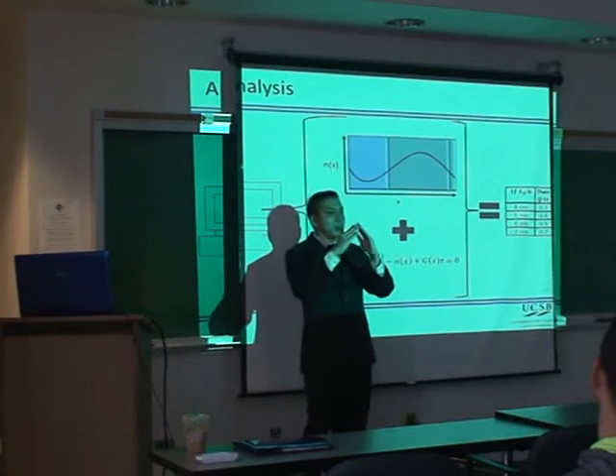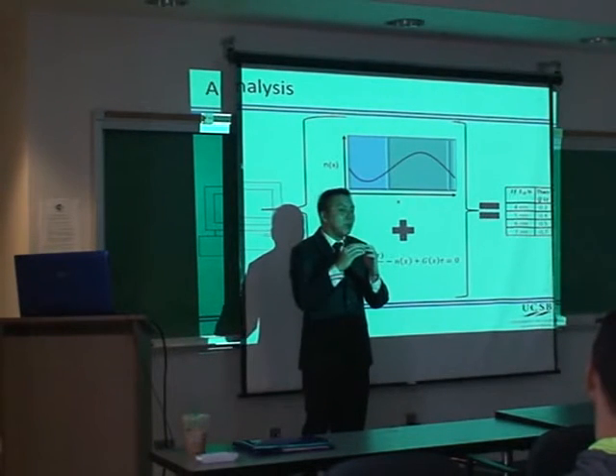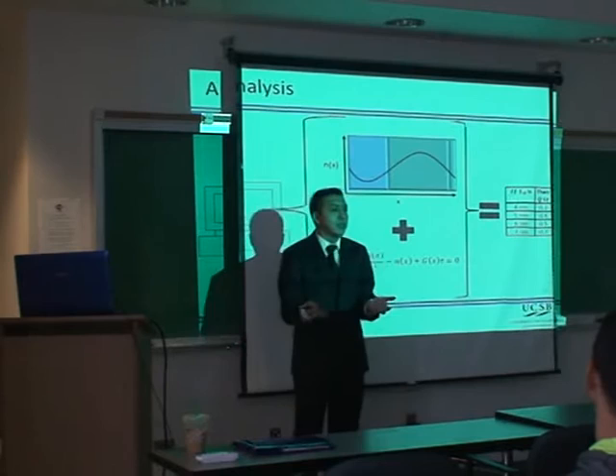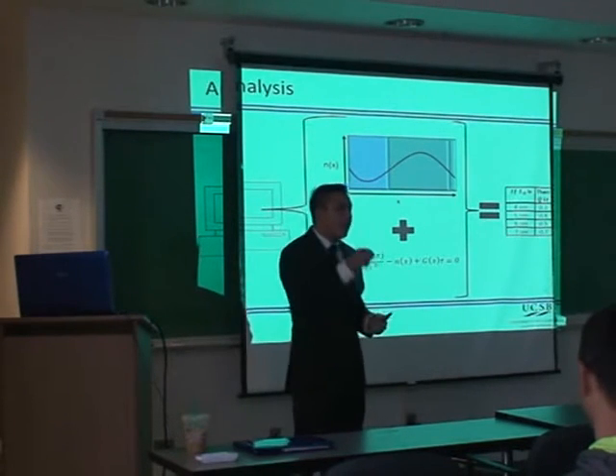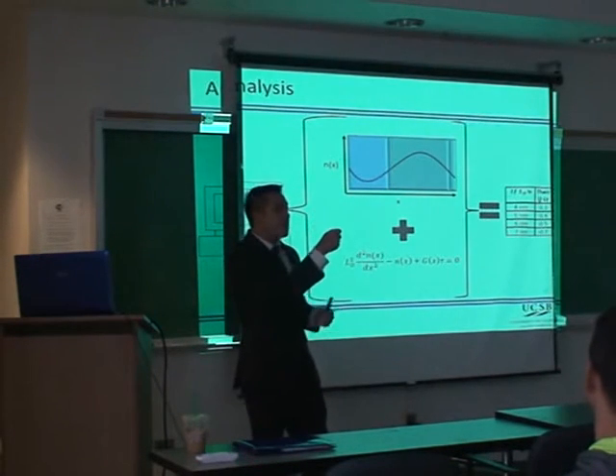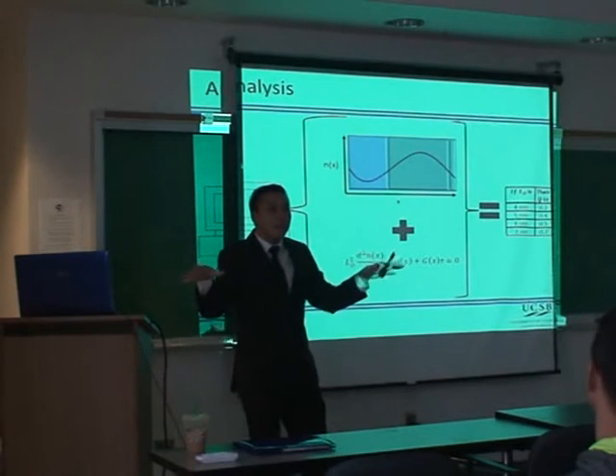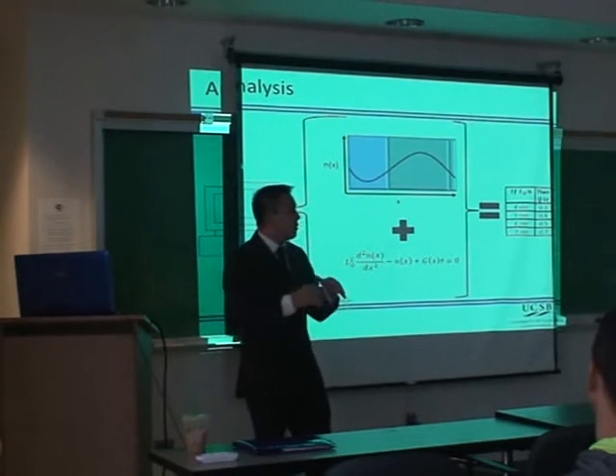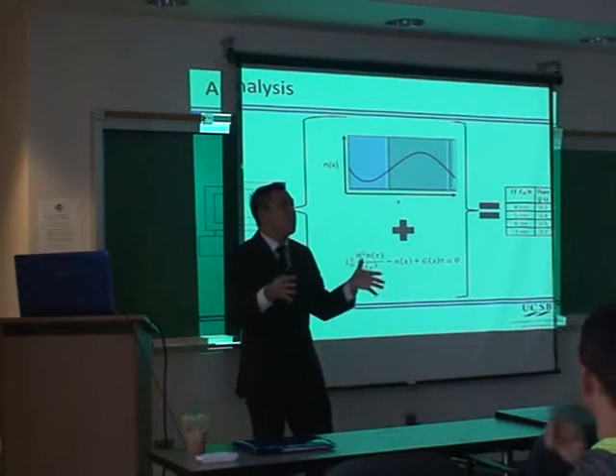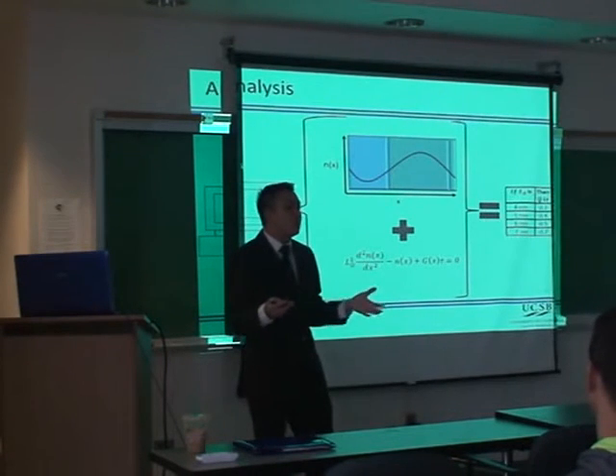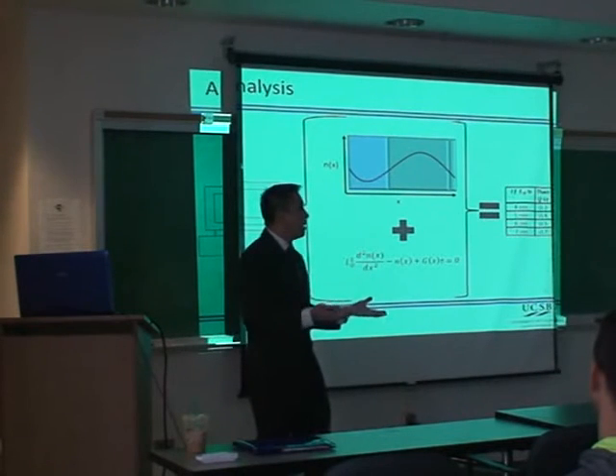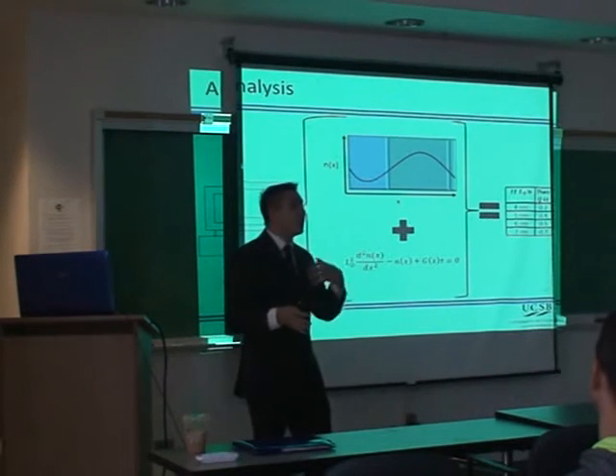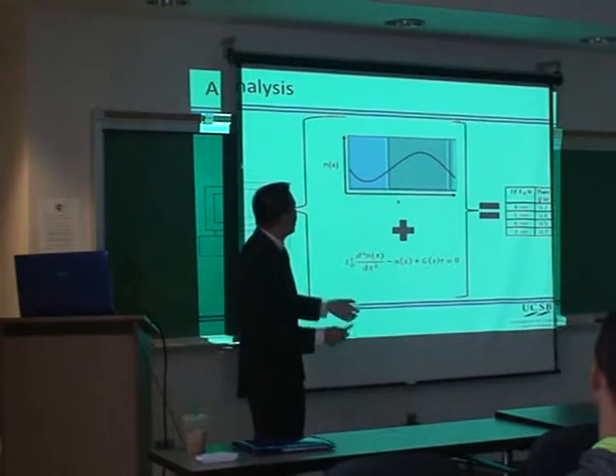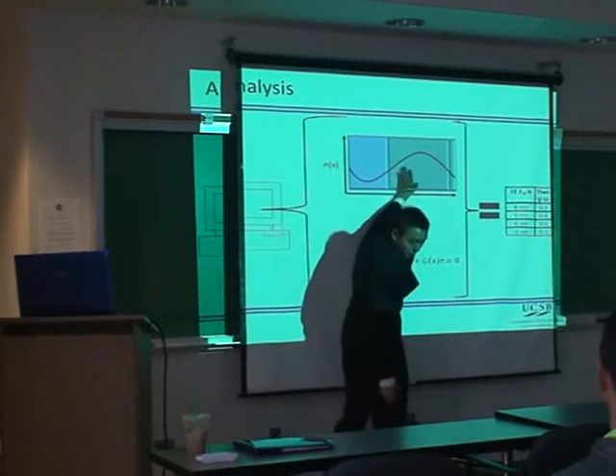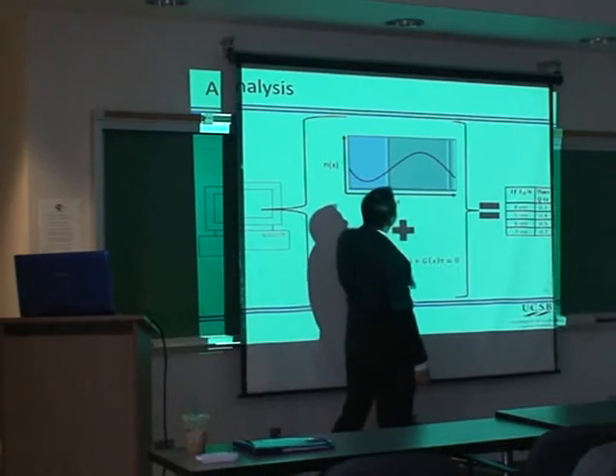You have this initial population. What happens? Well, how excitons move is through diffusion. An example of diffusion is when you add a dye into water. The dye starts off very concentrated and it diffuses out. But what's interesting about excitons is that not only does diffusion occur, but they also disappear. When you add dye into water, let's say a red dye, the water becomes pink. But in my case, the water will become clear again because the dye itself kind of disappears. That's kind of like saying that excitons will quench themselves.